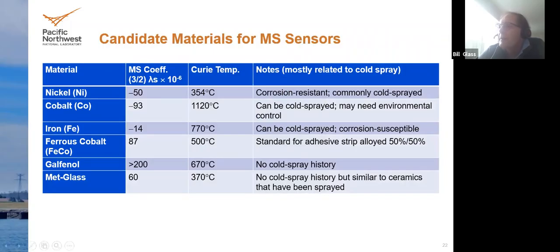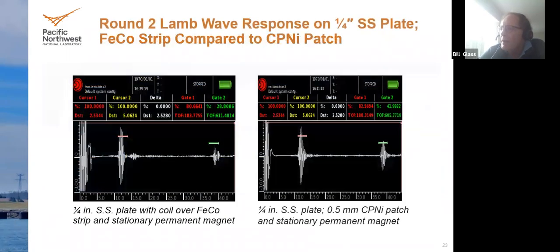So there are a number of possible materials that you can use for cold spray listed here. Some of them have higher Curie temperatures than others. This is an important consideration when choosing material. Most of the work that we did for initial qualification was with nickel, but here the demonstration was that on a cold sprayed plate, we can get a similar response, or in some cases even better, with the cold spray.